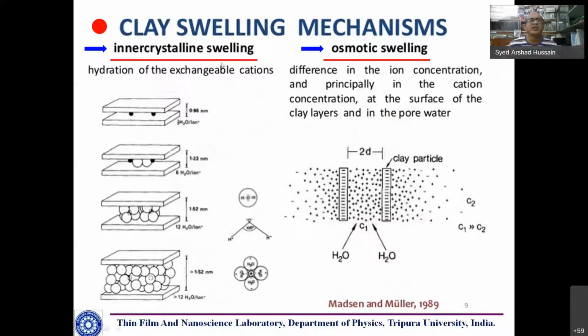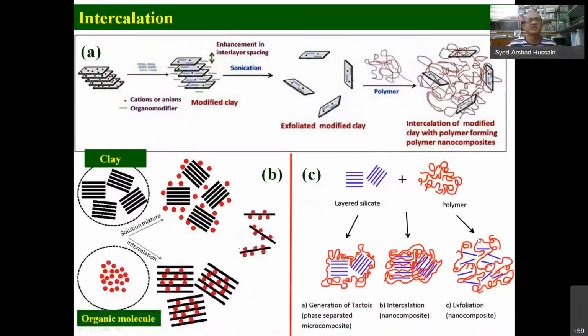The main mechanism in swelling is the hydration of exchangeable cations within the clay layers, and at the same time, sometimes osmotic swelling also occurs. This is because of the difference in ion concentration between the clay layers and the outside solvent. Due to this difference, the solvent goes inside the clay layer and they swell. That means the sheets separate from each other and form single sheets.